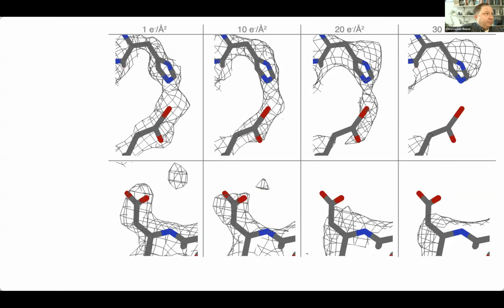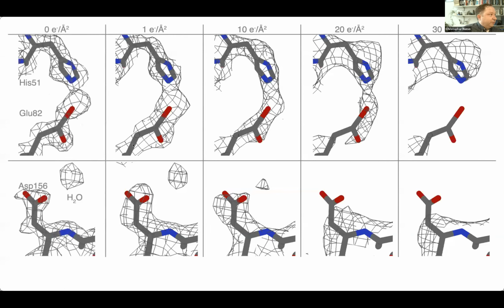Whereas all of the programs previously were basically throwing this away one way or another, either down weighting it or actually even omitting it. But there's something else we can do now that we have a proper physical model for both the movement of the specimen and for radiation damage of the specimen. And that is go back to before the first electron per angstrom squared. So actually reach back in time to before the electron microscope was turned on. So how do we do this? And you can see this is even better.